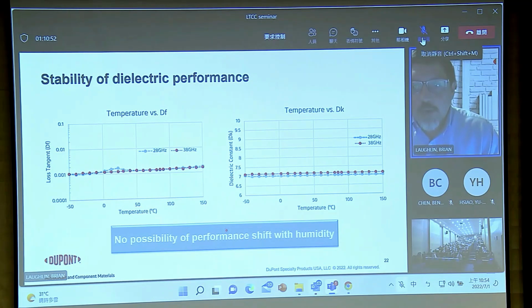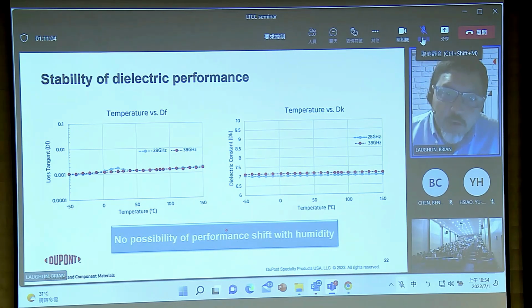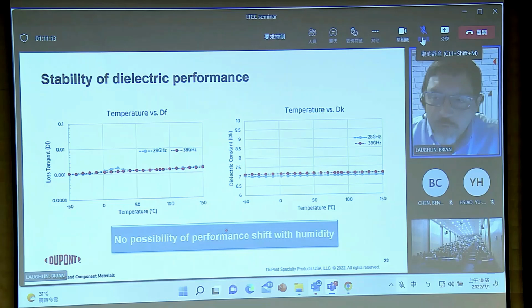Not only do you get that great dielectric constant and dielectric loss performance versus frequency, but it also is stable over ambient use conditions. So here at 28 and 38 gigahertz for 9KC, we show the dielectric loss tangent and dielectric constant from minus 50 degrees to 150 degrees, measured in situ. And here you see almost no change in the dielectric properties over the practical use conditions.